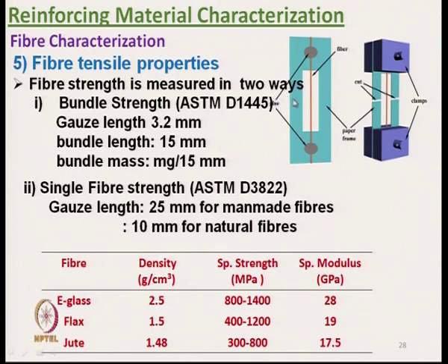One is bundle strength, that is by ASTM D1445, where gauge length is kept 3.2 millimeter and bundle length is 15 millimeter. Okay. This is the actual bundle length, but the gauge length is 3.2 millimeter and bundle mass is milligram per 15 millimeter. So, total bundle mass is measured. So, this is the way it goes.